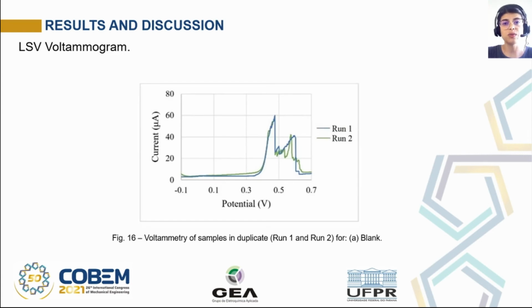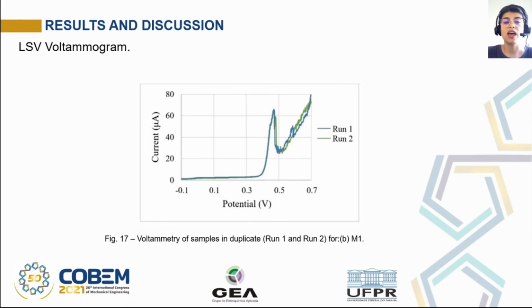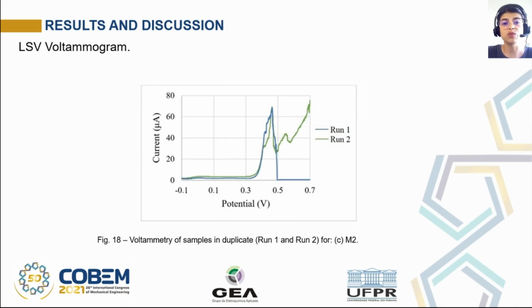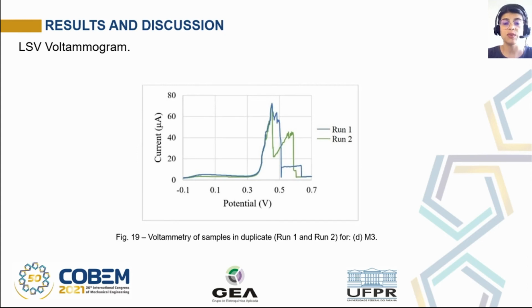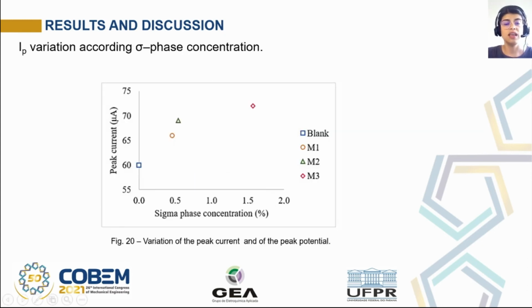To compare our results, we had one piece called blank, which has no sigma phase in its composition. Figure 16 shows the voltammetry for this sample, and for this sample, the peak current obtained was around 60 microamperes. The voltammetry for sample M1 is shown in Figure 17, and the peak current obtained is higher than 60 microamperes. For M2, the peak current was higher than 60 microamperes too, and for the sample M3, we have the highest peak current. In Figure 20, we can see the variation of the peak current as a function of sigma phase concentration.